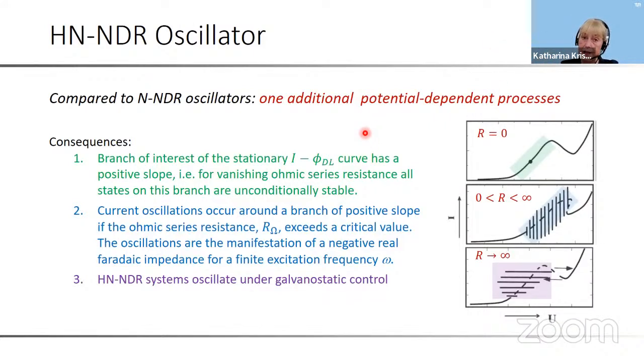The characteristic properties of HN-NDR oscillators, and H stands for hidden, is that the branch of interest of the stationary current potential curve has a positive slope, as indicated here. For vanishing ohmic resistance, all states on this branch are unconditionally stable. This is what we showed in the beginning, unless you have a very complicated chemistry. But so here, vanishing ohmic resistance makes a positive slope.